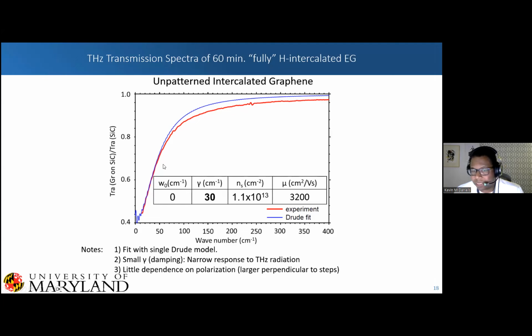So basically just looking at the Drude response, and we were able to fit this with a single Drude model. Which is pretty great, and we were able to show really narrow plasmon resonances of around 30 wave numbers. This is with a sample with a carrier mobility of around 3,200, and it really showed little dependence on polarization. It was a little bit larger perpendicular to the steps, which of course are scattering sites in graphene.